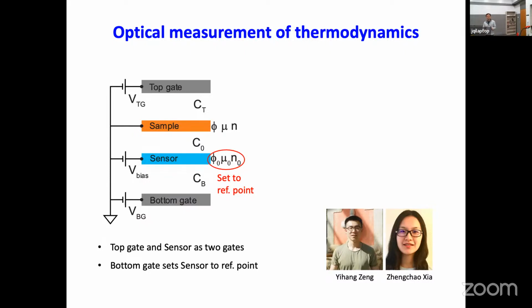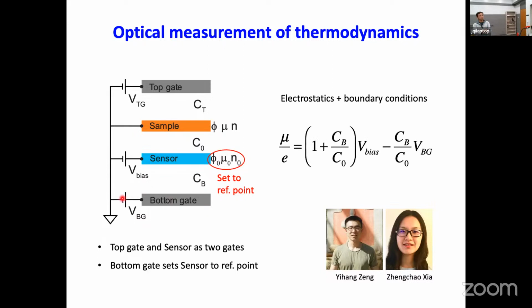If we can do that, the sensor here will provide a bridge and help us read out the chemical potential of the sample simply by using the backgate voltage that we apply to fix the sensor at a fixed point, and the bias voltage between the sensor and the sample. These two voltages, when combined, can be shown to be related directly to the chemical potential of the sample. And this ratio here is just the geometrical capacitances between this layer and that layer, the bottom gate and the sample to sensor distance there. That ratio can be experimentally calibrated very precisely.